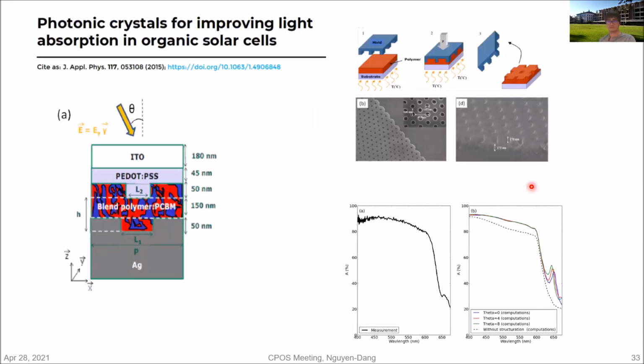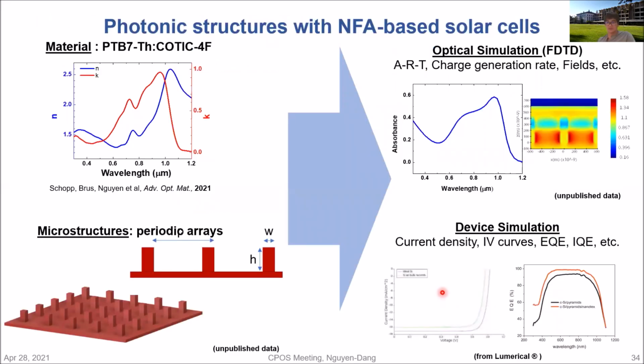Actually, there are people trying to do that, but not successfully. In one paper that I can find, they show some microstructure of the blend polymers with PCBM, traditional solar cell materials. They show a tiny peak at 650, so it still sits in the visible. Recently, there's a new type of solar cell, the non-fullerene solar cell, with the absorption as shown here. It absorbs really far into the infrared.